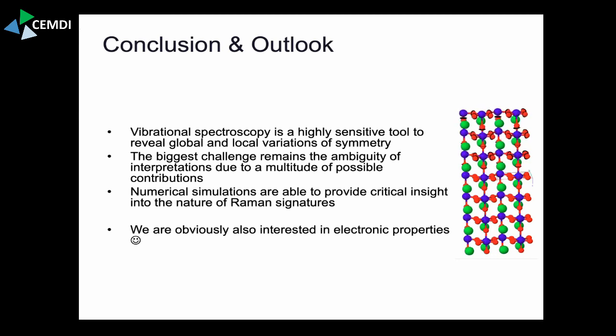So the first point would be that I presume it's metal surfaces. It can, yes. In principle, CO2 would dissociate, and I'm not sure if it's site specific. What I think could be feasible is to see whether the vibrational frequencies change depending on the orientation of the surface. For example, comparing two different platinum surfaces and looking at the vibrational frequencies. That's something we're looking into at the moment for MgO, looking at whether the stretching bonds of OH vary depending on the surface, whether it's 100 or 110 magnesium oxide. So the answer is, I would give it a shot, yes.